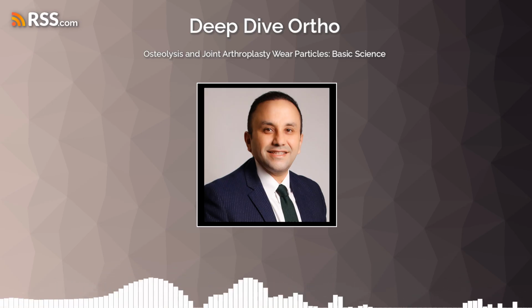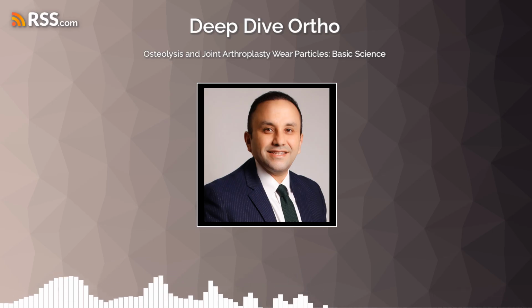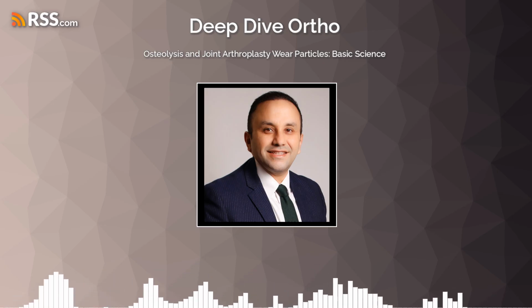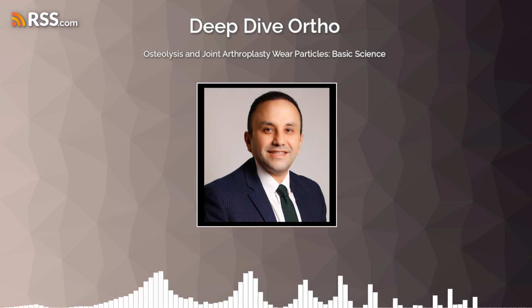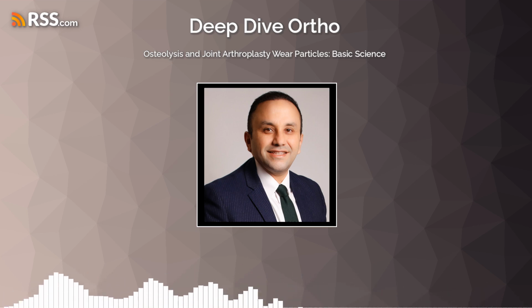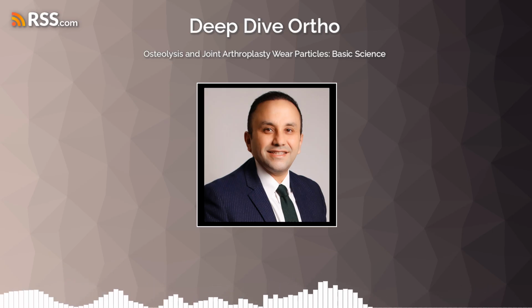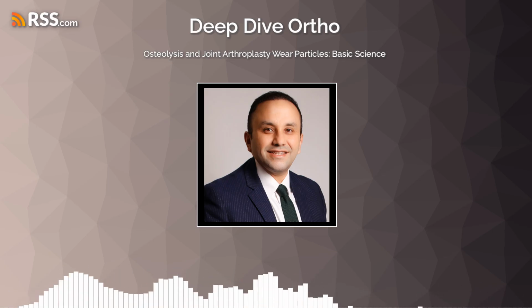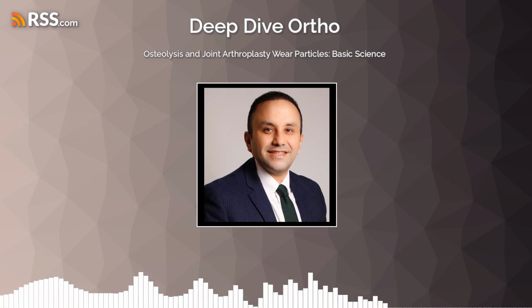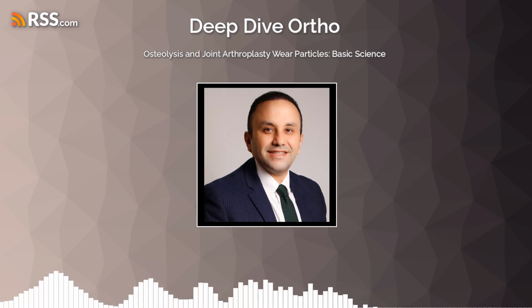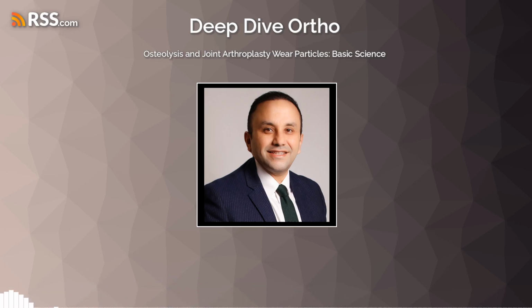Generally, yes. Factors that increase UHMWPE wear in total hip arthroplasty include a polyethylene liner thickness of less than 6 millimeters, which leads to higher stresses, component malalignment, and patients under 50 years old. Why younger patients? Likely due to longer exposure time to the implant and generally higher activity levels over their lifetime. Also, male patients and those with consistently higher activity levels tend to show more wear. Interestingly, while larger femoral heads increase volumetric wear, femoral head size between 20 to 46 millimeters in diameter does not seem to significantly influence UHMWPE linear wear rates.